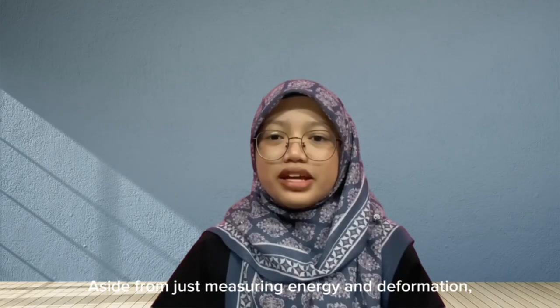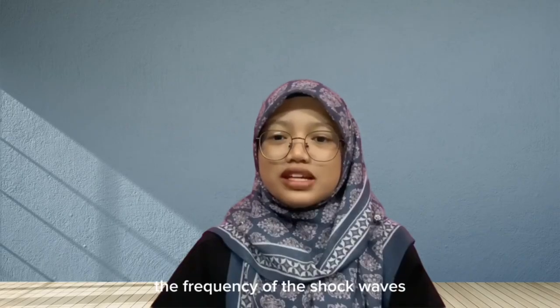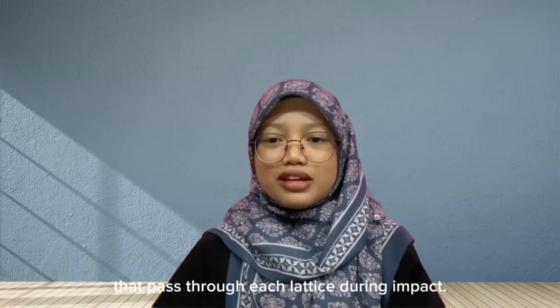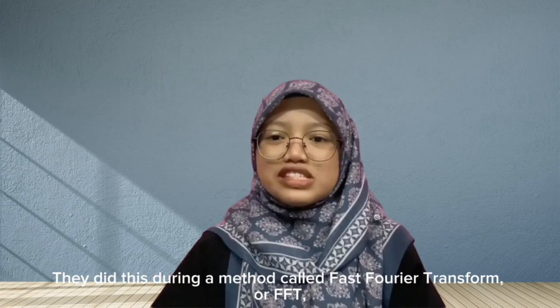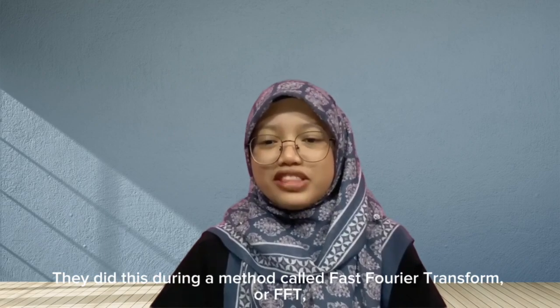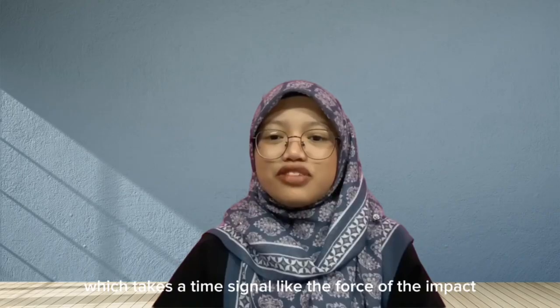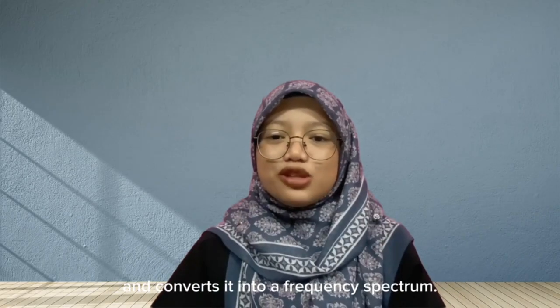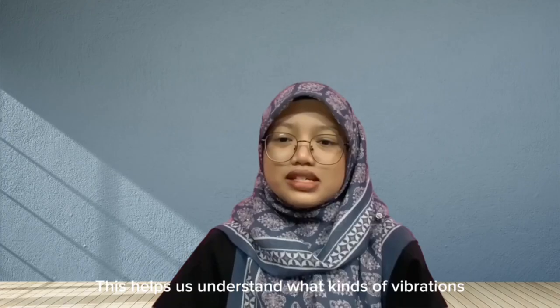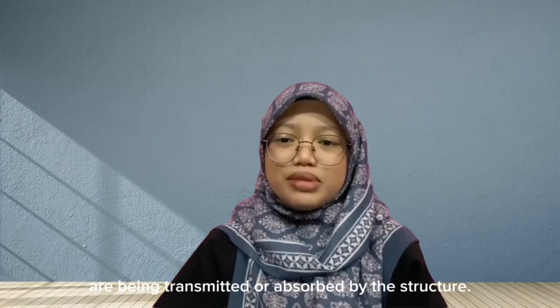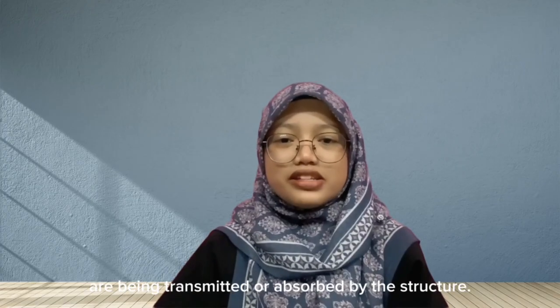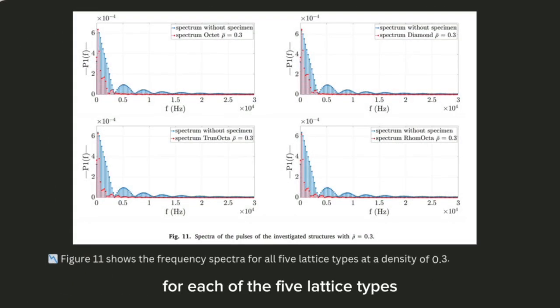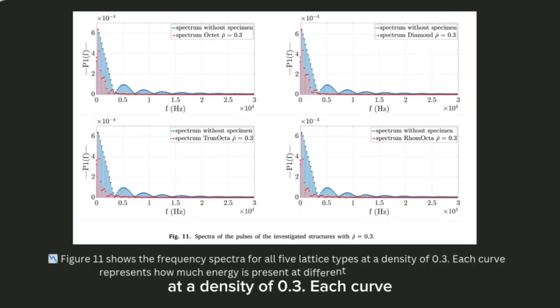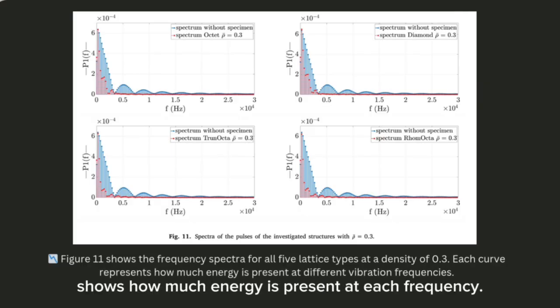Aside from just measuring energy and deformation, the researchers also analyzed the frequency of the shock waves that pass through each lattice during impact. They did this using a method called fast Fourier transform, or FFT, which takes a time signal like the force of the impact and converts it into a frequency spectrum. This helps us understand what kinds of vibrations are being transmitted or absorbed by the structure. In figure 11, we can see the frequency spectra for each of the 5 lattice types at a density of 0.3. Each curve shows how much energy is present at each frequency.